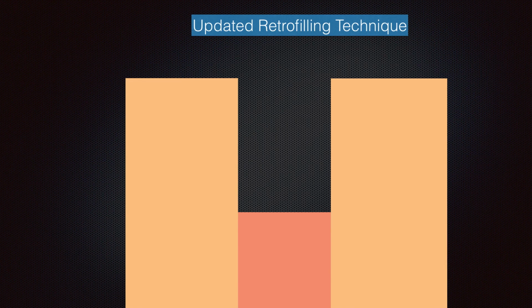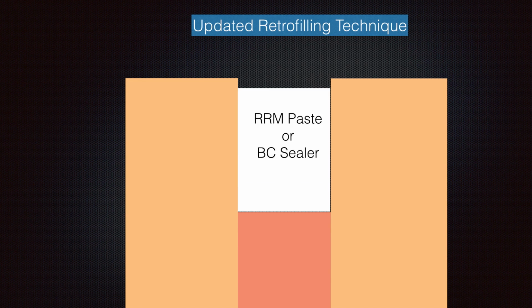And I've been using this right from the get-go, basically, right as soon as we developed the putty material. It was meant to do this particular thing. Originally, people were using the putty to fill the whole canal, but that really didn't improve the efficiency gains that you could have when you move up from MTA to this material. The best way to use this material is the lid technique, which involves injecting the syringeable material into the retropreparation and then using the putty for a protection cap up on top of this material.